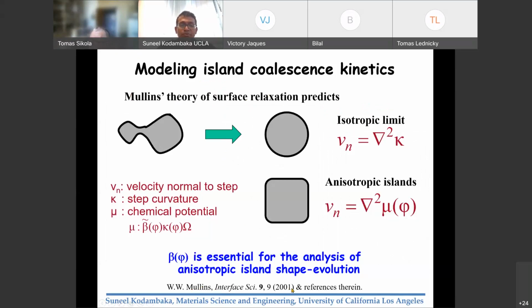Now, the theory of surface relaxation was developed by Mullins a long time ago. Actually, this is a relatively new reference, but the theory was developed a long time ago. It was assumed that any arbitrary shape would evolve into an isotropic shape, in which case the step velocity is given by the gradient of the curvature. But for anisotropic islands, where the step energy and step stiffness change with orientation, you cannot simply use this formalism. You have to take the chemical potential, which is now a product of step stiffness and curvature, both of which change with orientation.